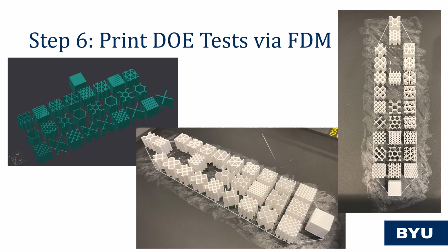However, due to the limitations of FDM printing, several of the designs were unable to print successfully because they were either too thin or too thick and resulted in improper adhesion to the bed or warping from the bed. In both situations, these extreme design samples were unsuccessful to print even after multiple attempts. The design of experiments, or DOE samples, were measured and the relative density was calculated against the bulk material.